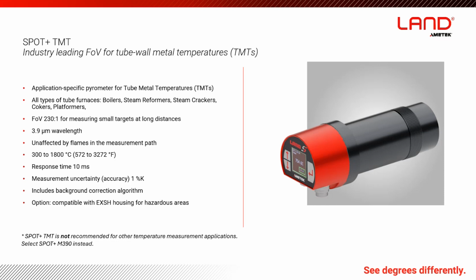Measurement range 300 to 1800 degrees Celsius, so it covers really any temperature that you'd want to measure within a tube furnace. 10 millisecond response time, very fast. Accuracy 1% Kelvin, it's got good accuracy, and it's got the background correction algorithm as well, because in a typical furnace you may have refractories that are at a higher temperature than the tubes that are carrying your reactants through the furnace.